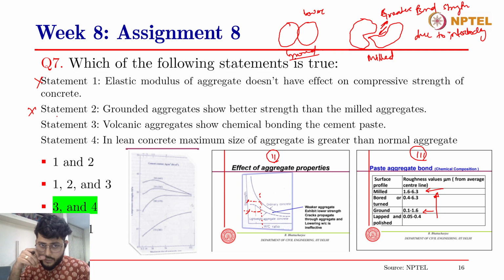Coming to statement 3, volcanic aggregates show chemical bonding in the cement paste. Yes, they generally show chemical bonding in the cement paste, because volcanic aggregates contain reactive silica in them, and they act as pozzolanic materials, as we have also discussed in the previous lectures. Volcanic ash was used in the old days in ancient Italian structures as a pozzolanic material. So volcanic aggregates, volcanic ash, contain reactive silica and alumina, and therefore they contribute to the pozzolanic reaction in the cement paste, and not just form a mechanical bond, rather they also form a chemical bonding in the cement paste. So statement 3 is correct,